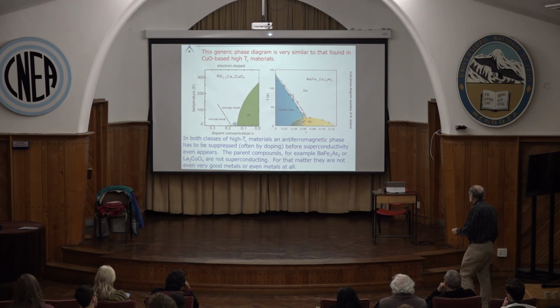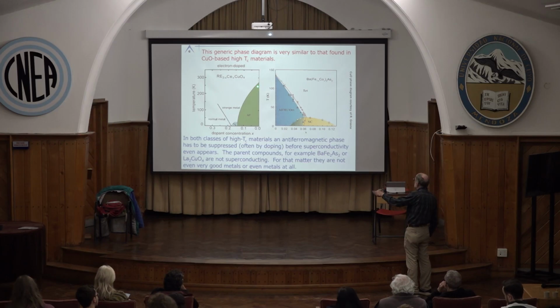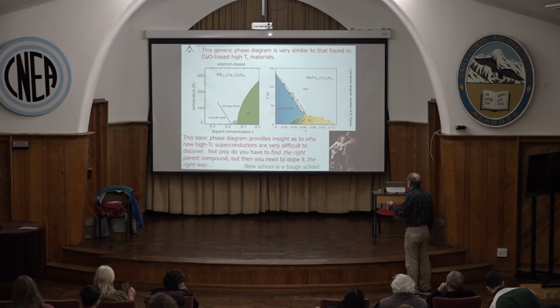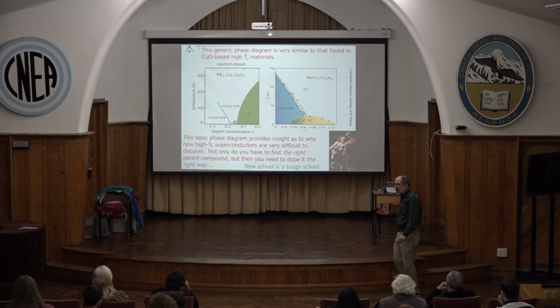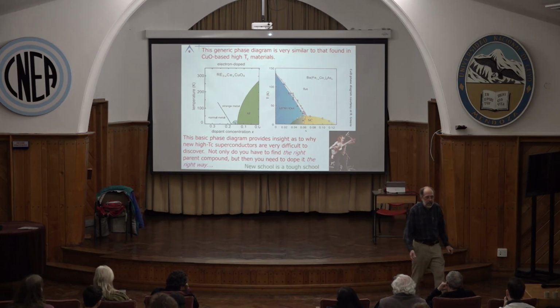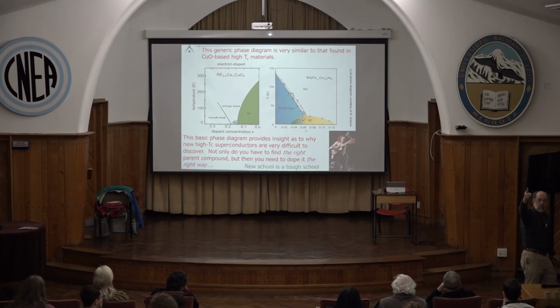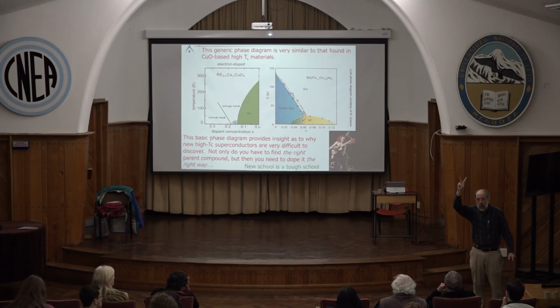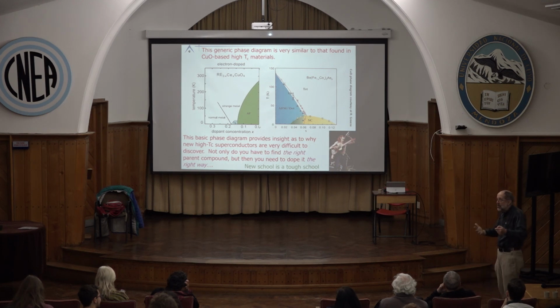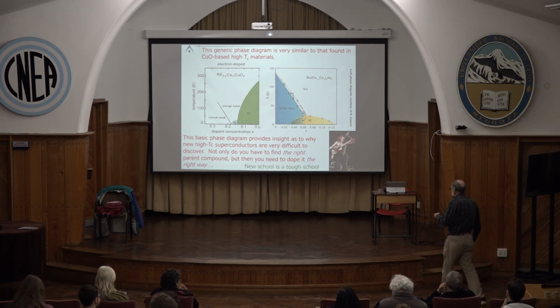The cuprates have antiferromagnetism. As you suppress the antiferromagnetism, you get a dome of superconductivity near where the antiferromagnetism goes away. Okay? Now, what's important to note is this is not even a metal. This is a crappy metal. Neither of them are superconductors to start with. Okay? So, this provides some insight into why we are finding so few high TC families. You have to find the right material and dope it the right way. That's the product of two small numbers, which my mathematician colleagues tell me is a very small number. Okay? So, this is one of the reasons it's a tough field.